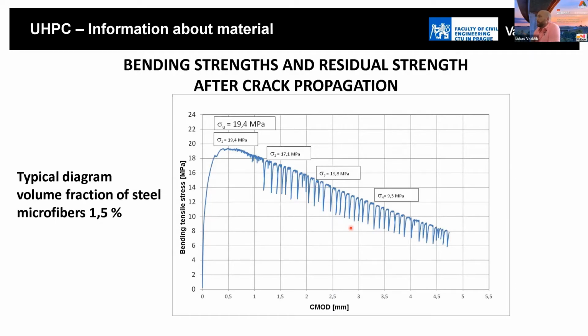If you compare the area under the blue line, it is something like the energy from the mathematical and physical point of view. And if you compare the energy, which is important if you want to damage or destroy this element in the tangent by the flexure tests, and you compare this area, this energy, with normal concrete, it is, for example, 10 times, 15 times higher compared to normal concrete. This is a great advantage of the UHPC.